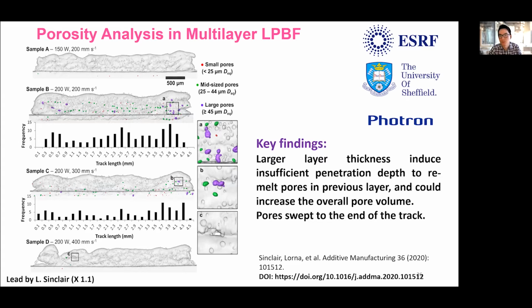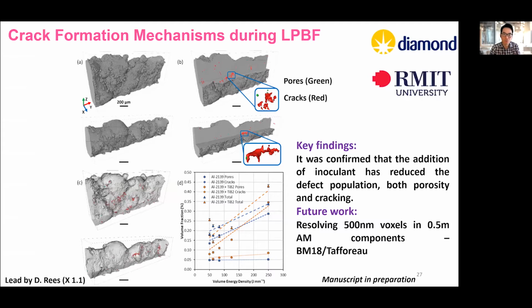So there's lots of research that's been going on behind the scenes. Observing these processes is one thing, but we also work with collaborators from Australia and others to try to come up with ways to mitigate some of these voids and cracks within the powder materials. So we're trying to add some additive onto the powder surfaces, or even pre-alloy them in the melt, so that we could potentially reduce the formation of these imperfections.